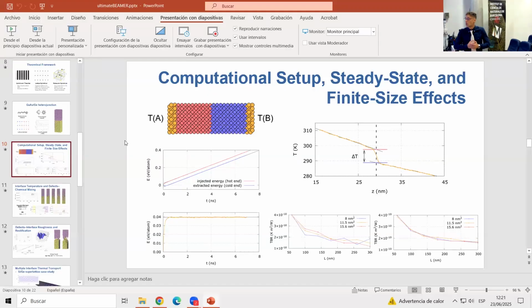I would also think that if you take materials with a very different thermal conductivity, if you can still obtain a junction forming in atmospheric condition, let's say, you would observe a higher rectification coefficient, but the system would be way less stable. So it would be probably even more difficult to then observe rectification in the experiments. I'm not sure if I answered, maybe I forgot something.